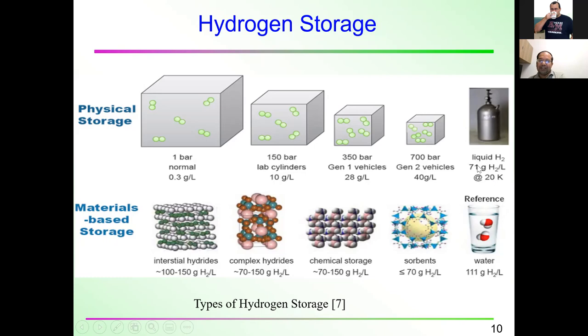The problem is that liquid hydrogen needs a very low temperature. You see here 20 Kelvin, that is around negative 250 degrees. For on-board application, it's quite impossible.